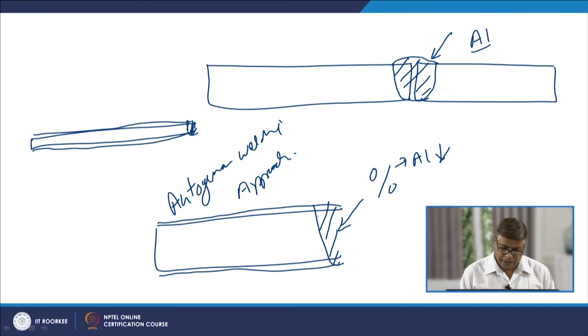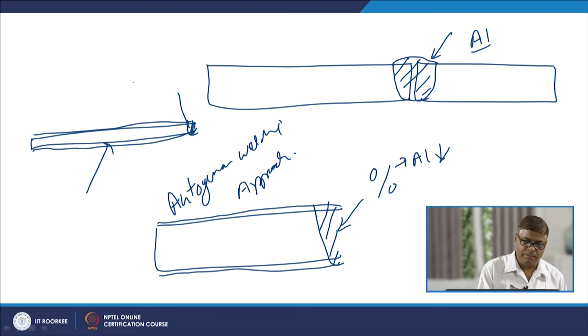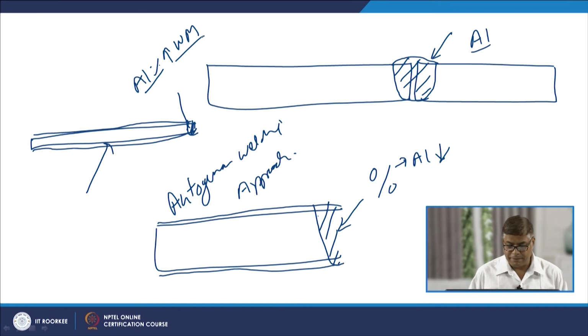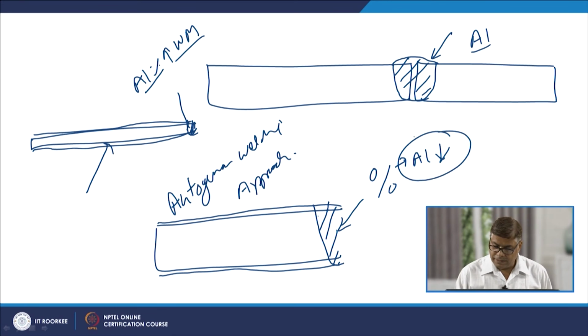So, for aluminized steels, when thin sheets are welded, in general the aluminum concentration in the weld metal is high as compared to the case when aluminized steel sheets of greater thicknesses are welded by the autogenous welding process. Then the aluminum concentration in the weld metal is less.